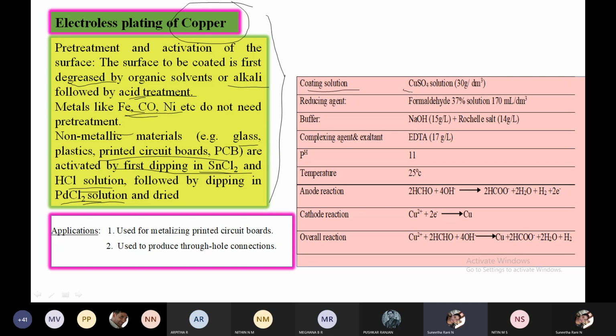The coating solution we are using, because this is electroless plating of copper, we have to coat the copper. So hence the bath solution we are preparing by using copper sulfate solution. What is the quantity? How much concentration? 30 grams per dm cube. So what is the reducing agent we are adding? The reducing agent we are adding is formaldehyde, which is 37% solution, 170 ml per dm cube.